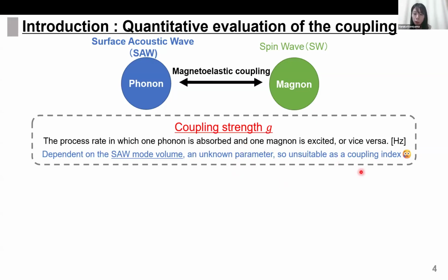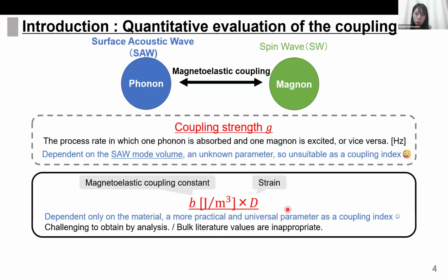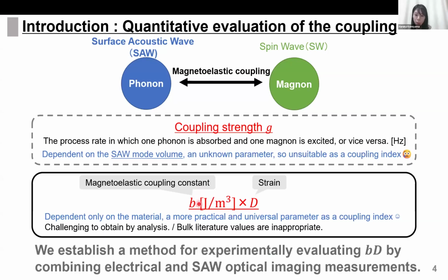Instead of coupling strength, we focus on the constant BD, which only depends on the material. B is the magnetoelastic coupling constant, and it has an energy density dimension. And D is a dimensionless constant that determines the magnitude of strain. Because BD depends on the membrane quality or the deposition method, determining the value analytically is difficult, and using bulk literature values is inappropriate. In this research, we establish a method for experimentally evaluating BD by combining electrical measurement and optical imaging measurements.